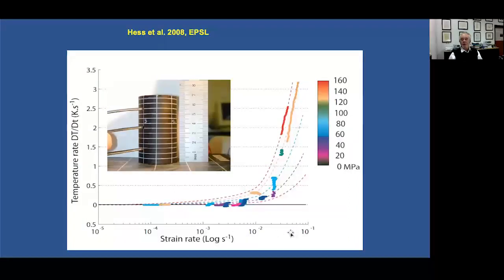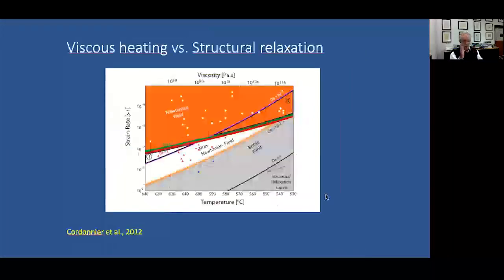So as we go to extremes of strain rate here, we actually start to drive ourselves into the regime of shear heating. And this is something which complicates the fragmentation and the explosion in these systems, because if we shear heat enough, we can avoid the glass transition. We can push the glass transition away from us by decreasing our viscosity through the temperature dependence of viscosity. So we fall back into a liquid behavior due to the fact that we're shearing ourselves and producing the frictional heat inside of the material, which we call shear heating.